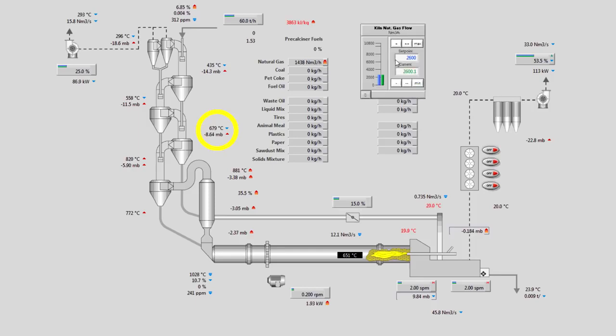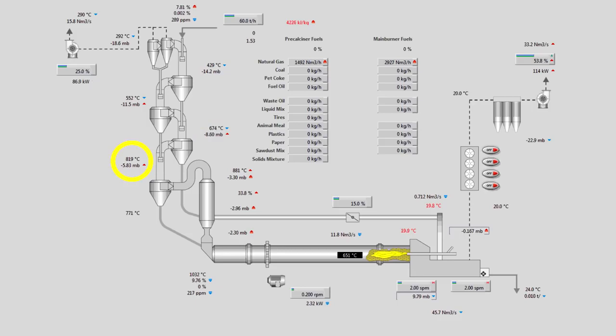I am also increasing the burning zone fuel. We need to prepare it for when the material reaches it. Material is now at stage 5. Obviously the preheater ducts are very large and I still do not have enough gas flow. It looks like some of the material discharged by stage 3 fell through directly into stage 5.